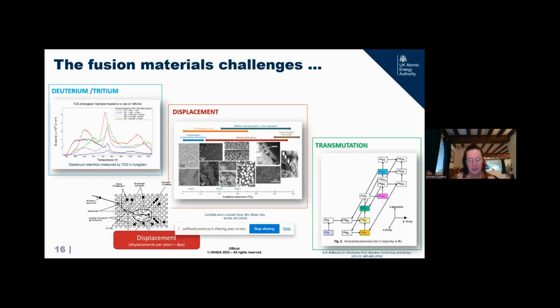And as they knock each other, there is a knock-on effect, and you can build from a point defect to a dislocation, a line defect. And those can aggregate and move towards grain boundaries in the materials, and you start to see bigger defects. And we see voids, and we see cavitation, or we see changes in the dimensions and the volume of the material, and we see swelling. And all of these things have been really well documented by an excellent Professor Steven Zinkle in America at Oak Ridge National Lab, who has led the way internationally on this understanding of the variety of phenomena we would see as a result of neutron imposed displacement in materials.